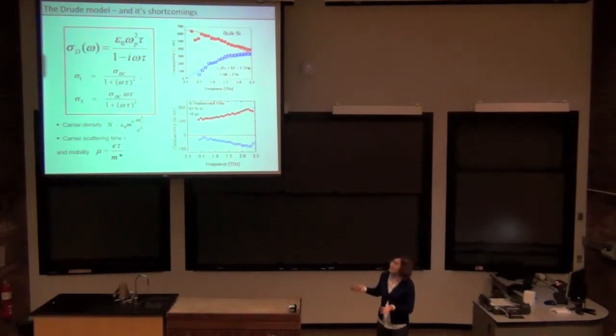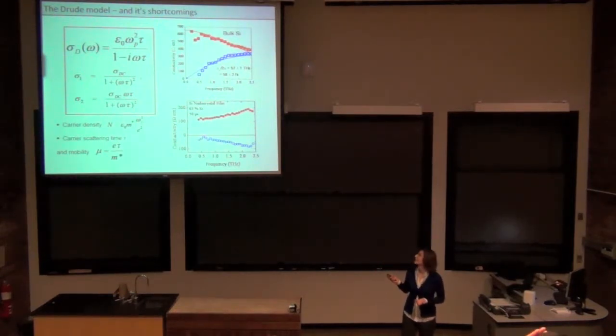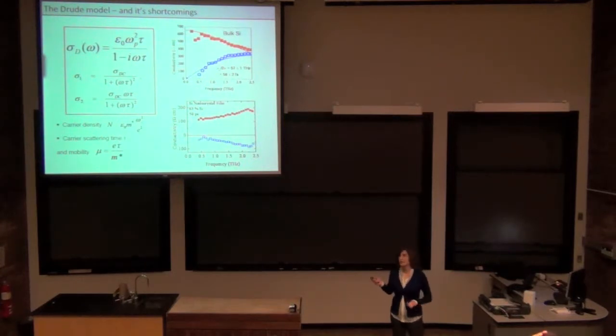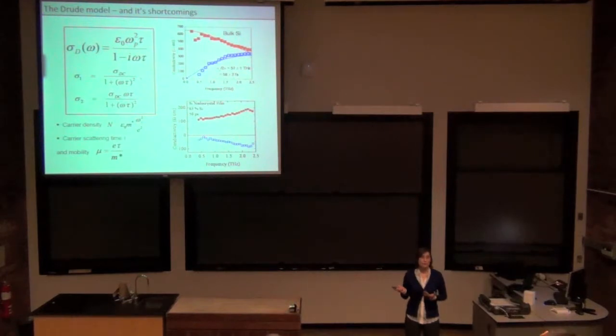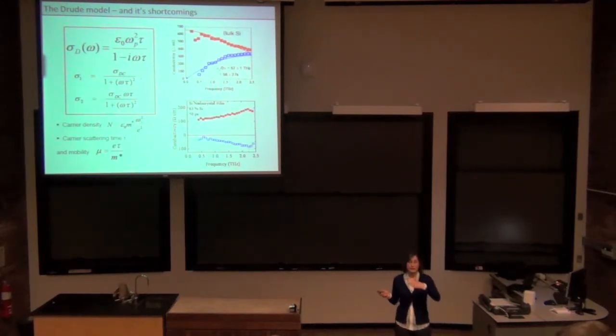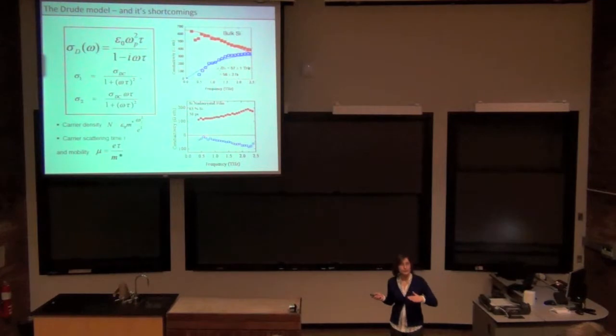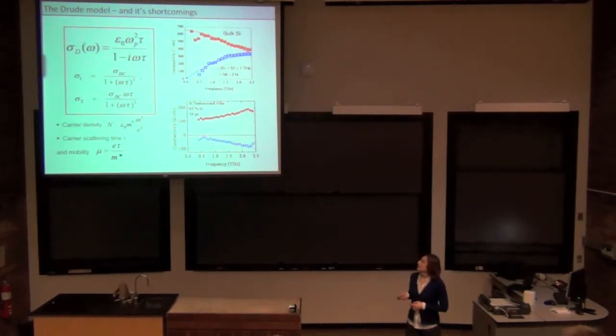Okay, so then we look at, of course, silicon nanocrystals. This is what we get for one of the 50 picoseconds after photoexcitation. So there is a problem. Of course, there's absolutely no way this can describe this. First of all, you now get this real conductivity that is suppressed at low frequencies, and you get imaginary conductivity that goes negative.